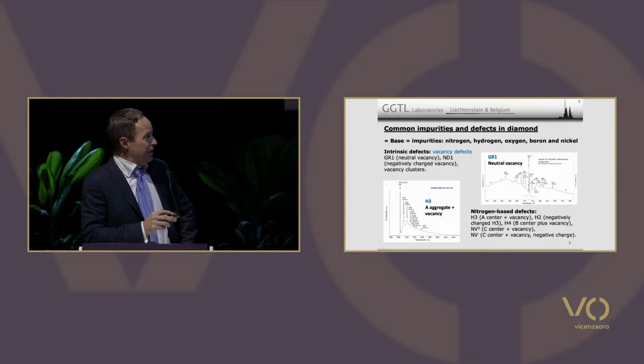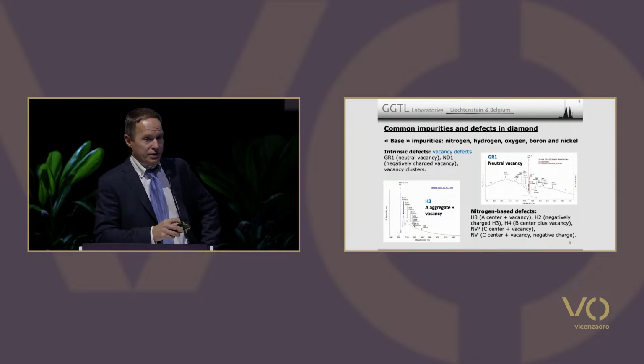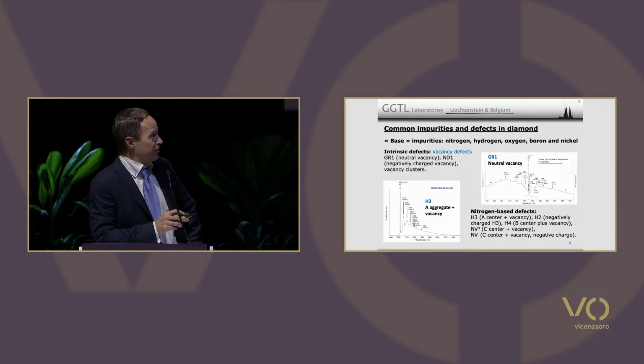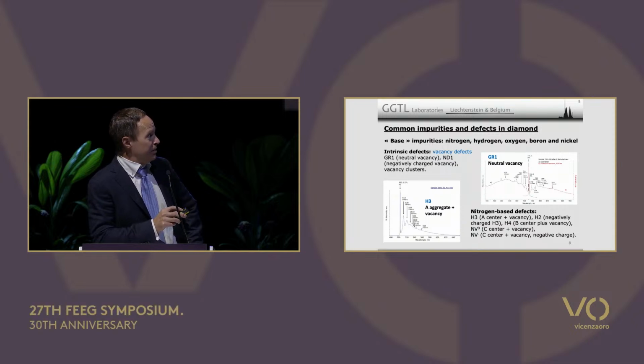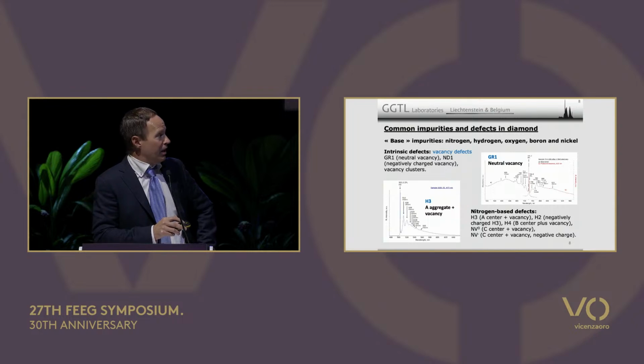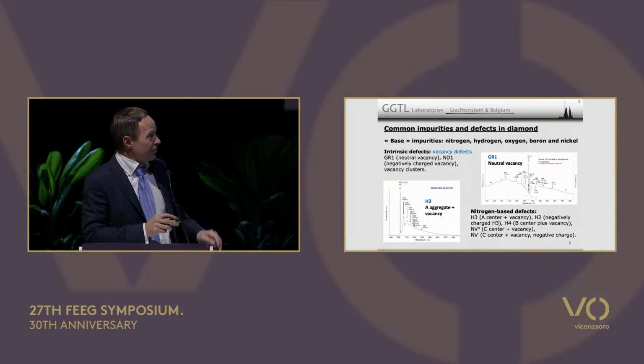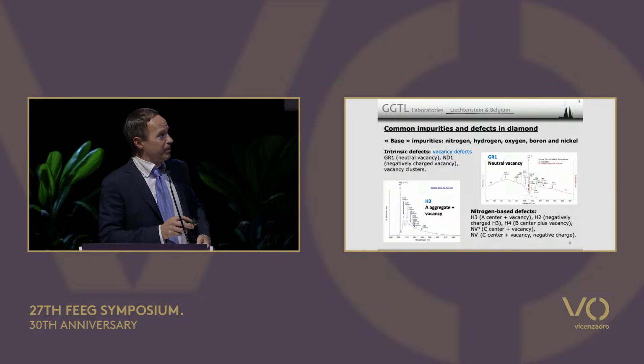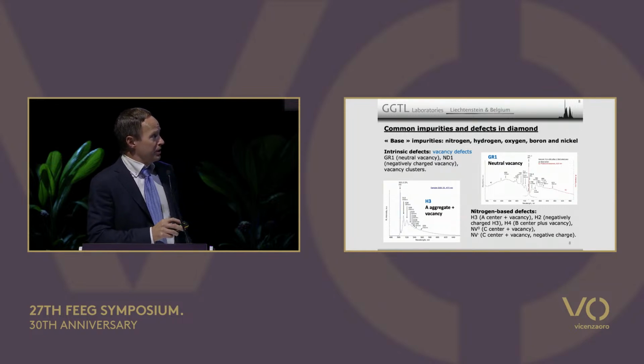Absorption spectra and luminescence spectra have the same zero phonon line. Here, this is GR1. They both have the same zero phonon line, but in absorption, you will have the vibronic bands at higher energy, lower wavelength, and in luminescence, you have them at lower energy, higher wavelength. Oftentimes, these spectra are almost mirror images of each other. Here, not quite, for a range of reasons.